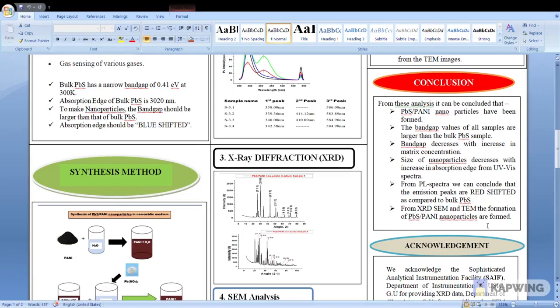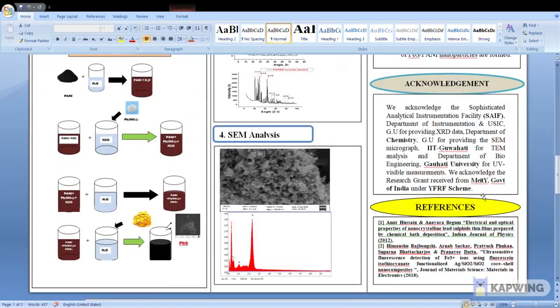From PL spectra, we can conclude that the emission peaks are redshifted as compared to the bulk lead sulfide nanoparticles. From XRD, SEM and TEM, we can confirm the formation of lead sulfide PANI nanoparticles.